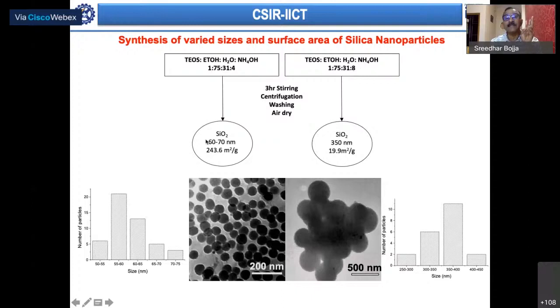When you look at the surface area, the particles which are 60 to 70 nanometers have a surface area of about 240 meters square per gram, whereas the 350 nanometer particles have about 20 meters square per gram, almost 10 times less. So the surface area responsible for catalytic activity is much more in the 60 to 70 nanometer particles, making them better catalysts compared to the 350 nanometer particles. That was one observation we tried to present in this work.